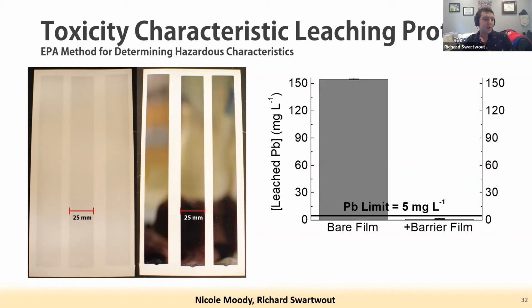If you take the bare film, printed on PET, it does not pass EPA regulated TCLP testing. But the barrier film gives about a 100 times reduction in leaching, and most significantly would actually pass EPA TCLP hazard testing in this scenario. We think this is very important, so we're pursuing IP protection in case anyone's interested.